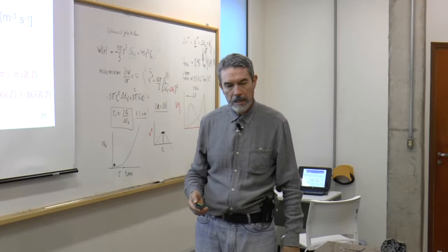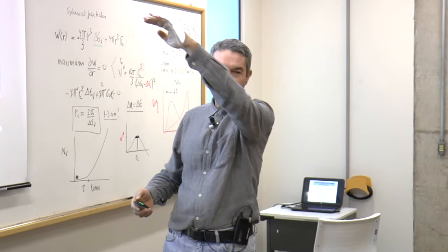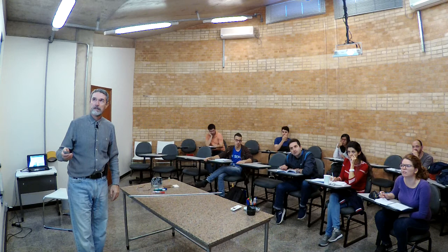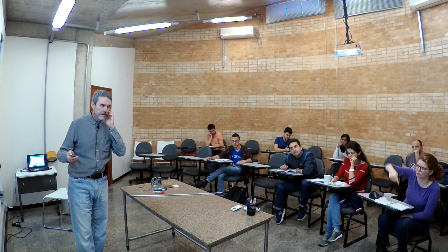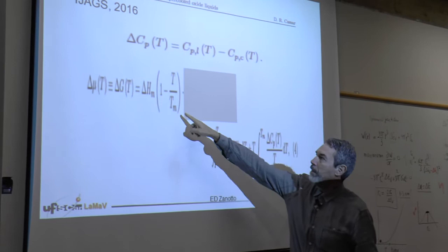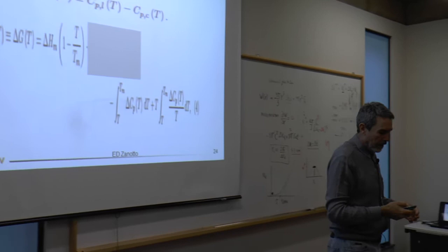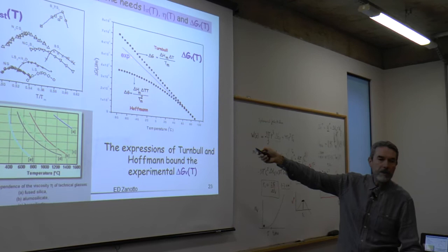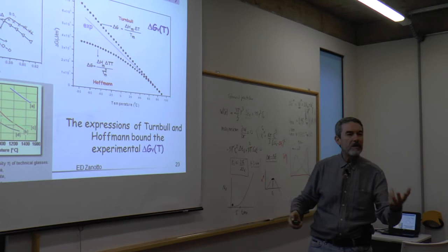It's a little bit curved. That's a schematic, but it's slightly curved. We also need to fit... No, no, you're going to calculate it. You're going to use this expression and calculate it. There is no fitting, nothing. Just calculate. You are going to insert delta Cp here, the melting point here, and delta Hm here. To make sure that you're doing this correctly, you can calculate this upper bound and the lower bound, and your values should be in between. Because if you use some wrong values, it'll be here or here, and you know that you're not doing it correctly.